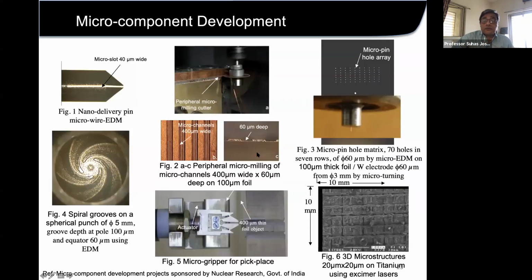Parallelly, we were also doing a lot of collaboration with Bhabha Atomic Research Center, and a lot of components we were manufacturing that was going on up to 2015 or so. Some of the components, like this, is a nano delivery pin, where a 40 micrometer slot is carved inside a pin, so that when the pin goes into DNA liquid, by the capillary action, it absorbs a small amount of liquid. And when it touches the nascent surface, it releases a small fraction of that. And that small fraction is a nanoliter, something like that. So there are many ways by which we actually fabricated these pins.